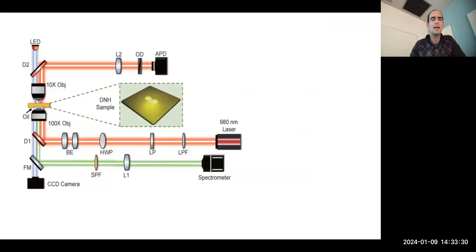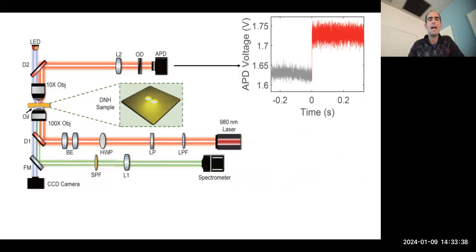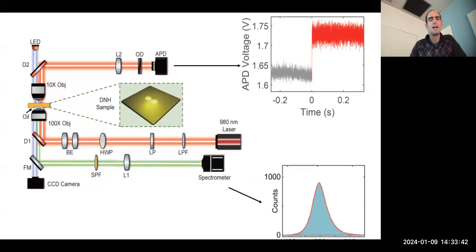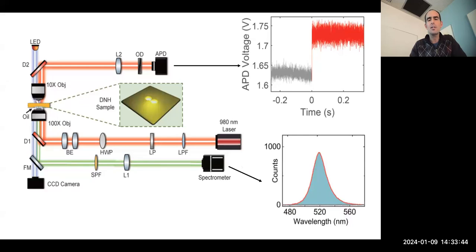We did essentially the same experiment. We have an optical tweezer system, which is just a microscope with a 980 nanometer laser. When we get trapping of these quantum dots, we see a jump in the transmission, and we see emission at around 520 nanometers, which is the wavelength of these quantum dots.